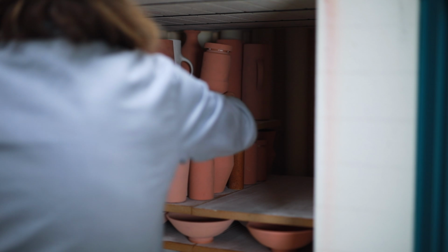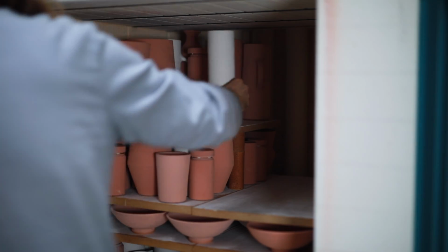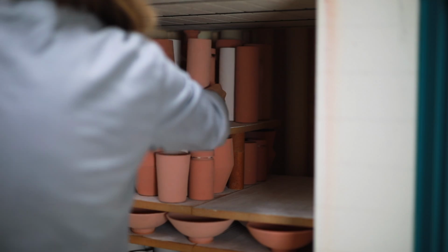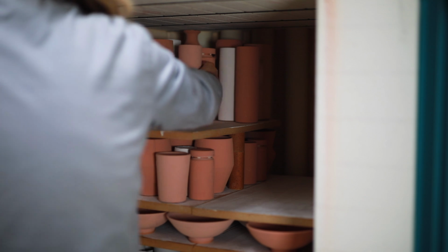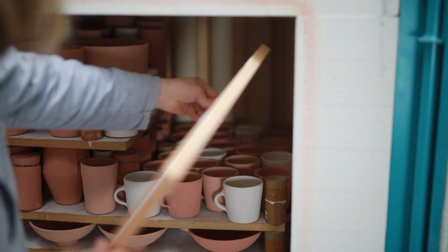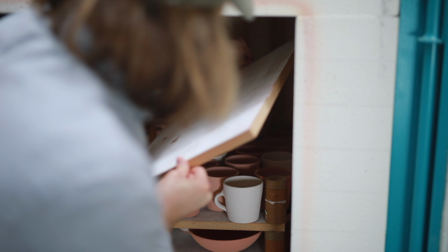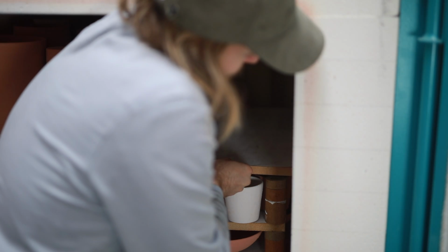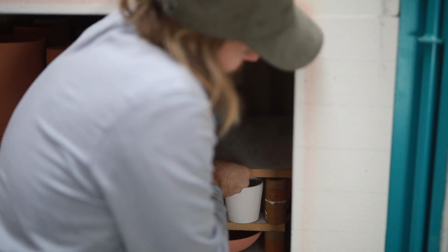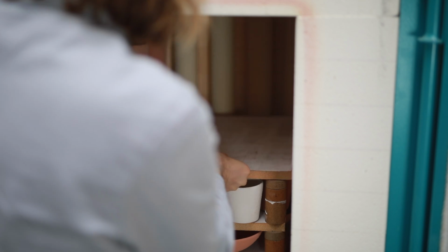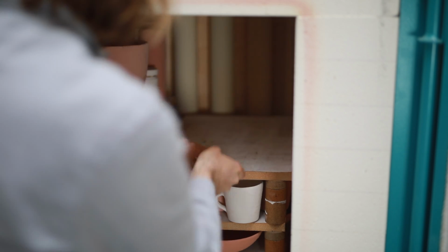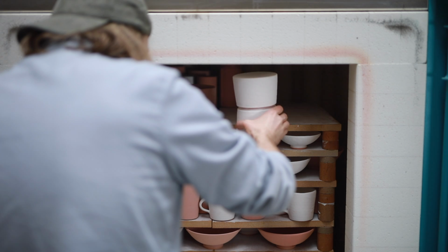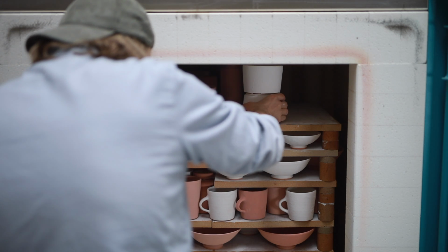The layer of glaze on these vessels at this stage is incredibly delicate. One small knock or error can cause a whole area of it to chip away, so I have to be incredibly careful during this entire process, which makes getting these shelves in at awkward angles all the more difficult. Thankfully, the glazes I use are very stable. They barely run at all from where they're put, so I don't have to worry too much about cleaning up the shelves after these firings.